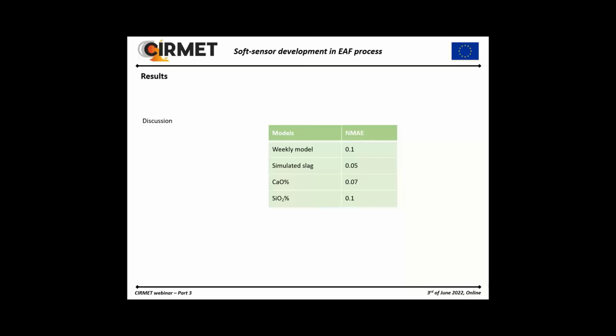So we can see that the lowest value was achieved for the simulated slag model, continues with the lime percentage, and the worst was for the weekly model and for the silicon oxide percentage. So these relatively modest results were obtained in the case of the weekly model. We think that it's because of the low quantity of weeks that we have, only 26.